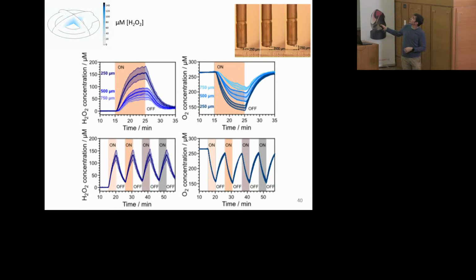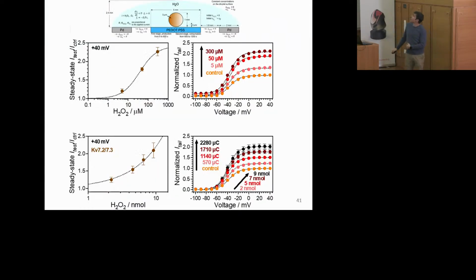So for example, this is the actual profile of peroxide concentration that forms. Over the course of several minutes, you can see that peroxide concentration grows. Meanwhile, we're consuming oxygen, so oxygen is going down. We're using up oxygen and creating peroxide. We measure this using these amperometric probes. And what we did successfully is we actually had this oocyte in the center of this pixel.